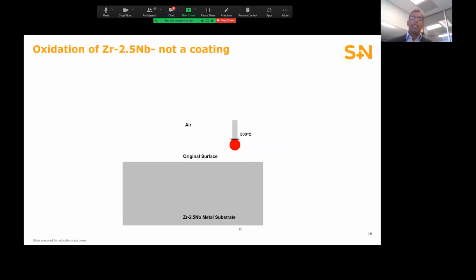So both oxidized zirconium femoral heads and knee femoral components are fabricated from zirconium 2.5 niobium. After the implants are machined, they're heated in the presence of oxygen, so in the air. This causes oxygen to diffuse into the material, ultimately transforming the surface to zirconium ceramic oxide.